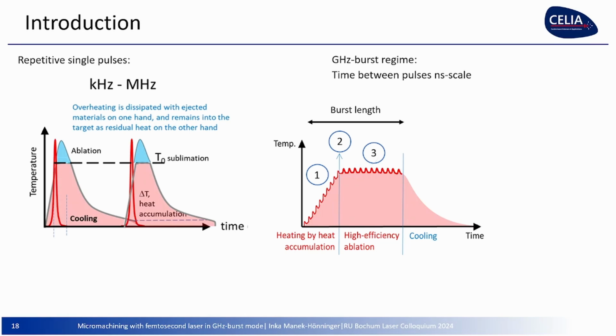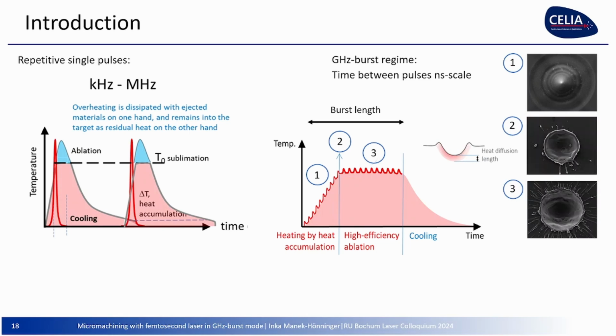So you have these three stages that I showed you, with their three corresponding features. The bump is formed due to heat accumulation; due to the heat there is some stress in the material, forming the bump, really like when you heat up for welding. This is how it is understood up to now. I have to admit that the GHz-burst regime is not fully understood. There is no theoretical model to date describing really what is happening.